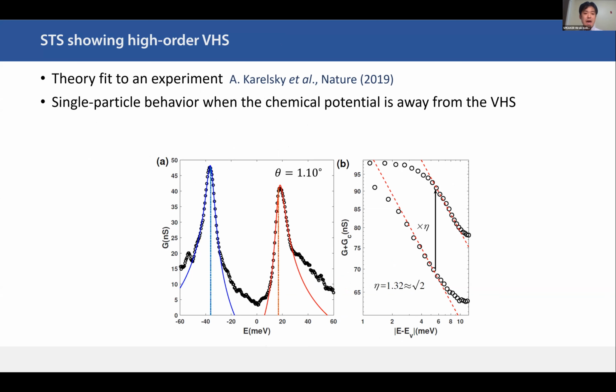Now we see how high order Van Hove singularity appears in a real material, twisted graphene. We try to fit the STS data using our density of states spectrum for high order Van Hove singularity. And this is the fit to the experimental data. The circles are from the STS measurement, and the solid lines are our theoretical fit. We can fit very nicely around the magic angle 1.1 of the experimental data using the high order Van Hove singularity. And we also see the asymmetry of the electron and hole sides. For the model of twisted graphene, the factor of the asymmetry is actually square root of 2. This is a log plot corresponding to the Van Hove peak and the electron side of the peak. And we also see a ratio of square root of 2, which corresponds to our theoretical estimate.